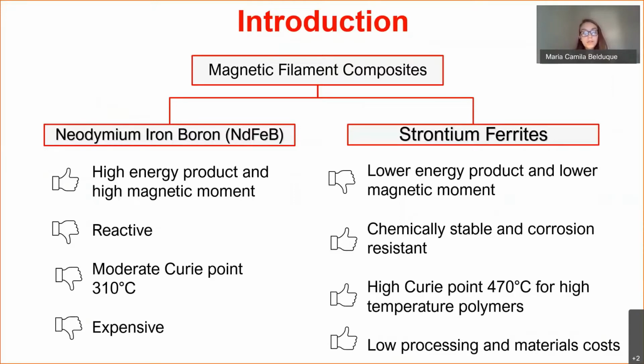all types of composite filaments with these instruments, researchers are exploring the area of magnetic materials for 3D printing applications and their mechanical properties with fillers such as neodymium and ferrites. Compared with neodymium, ferrites have a lower energy product and lower magnetic moment per volume density, but they are chemically stable and have a high corrosion resistance, which results in more durable parts. They also have a Curie point of about 470 degrees Celsius, which means that their working temperature is higher and can be added to polymers with a high melting point. Additionally, strontium ferrite has a lower processing and materials costs compared with neodymium and also nickel magnets.